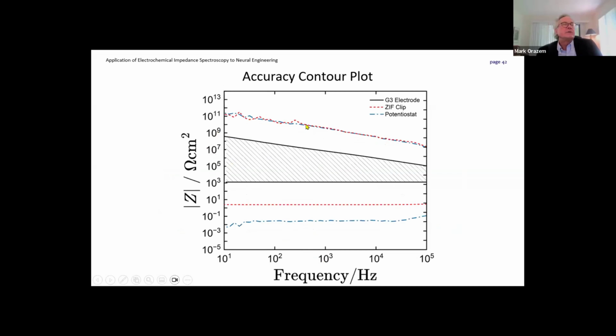Out here, we're seeing the potentiostat. They're using an AutoLab instrument. So we're seeing the high impedance region where we're making open circuit measurements. And down here, we're seeing the low impedance region where it's a closed circuit measurement. They used alligator clips that were clamped together, which adds at least a milliohm impedance. So the better thing to do would be to use banana plugs plugged into a block of copper, like I showed you in the previous slide. But we don't care about that because we're focused on the high impedance part of this system.